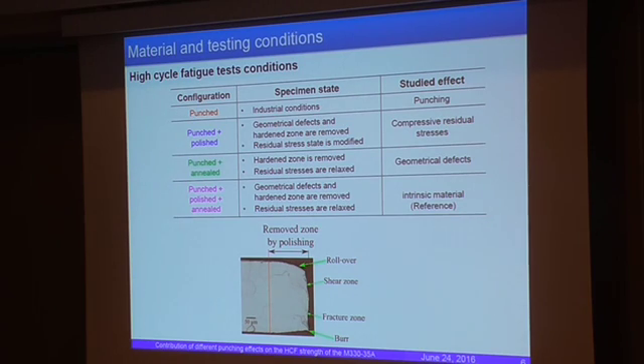The third and fourth configurations are the same as the first and second, but with stress relief heat treatment. So, in the third configuration, we remove hardening and we relax residual stresses, so we only keep the geometrical defects. And finally, if you get a punched, then polished, then annealed specimen, you remove all of the 3 effects and you get what we will use as a reference and what we expect is our intrinsic material.